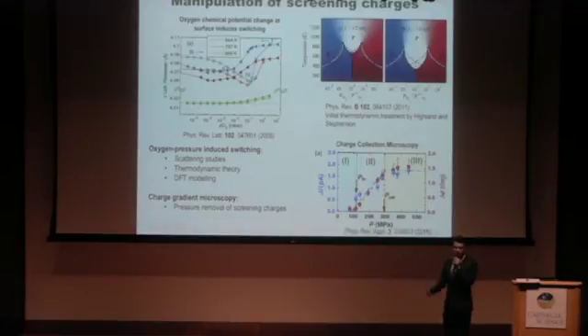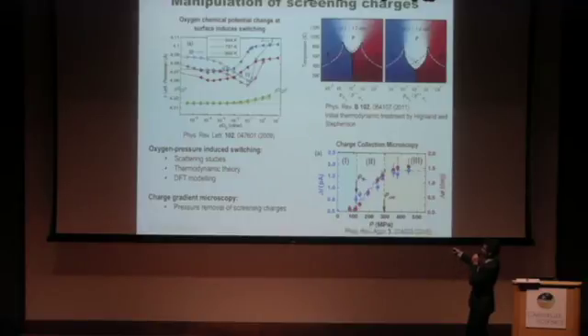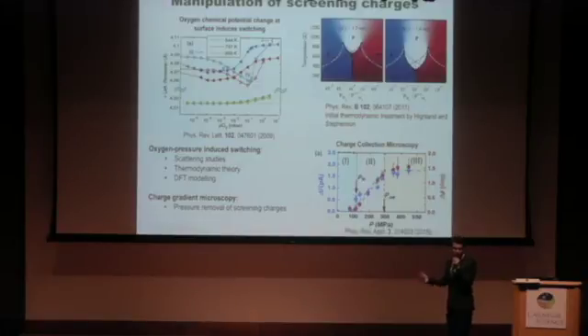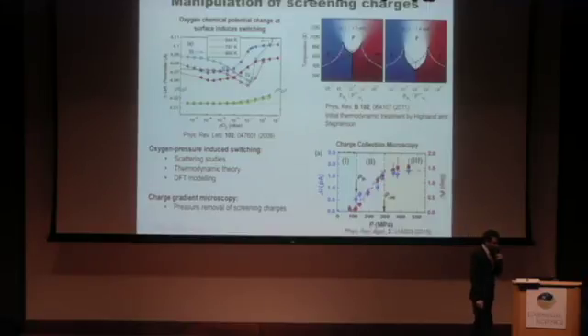So without applying any electric fields, they're able to switch their polarization. So this obviously has something to do with screening on the surface. They did some calculations and the initial thermodynamic treatment, and what they found was, for this particular thickness of lead titanate, there are different states of polarization that are preferred under different partial pressures of oxygen, right? So this is exactly what they saw in experiment. This is also relevant, for example, for so-called charge collection microscopy, and I can point to a review. That's work that again happened from Argonne and Sungbom Hong, who's now at Korea.